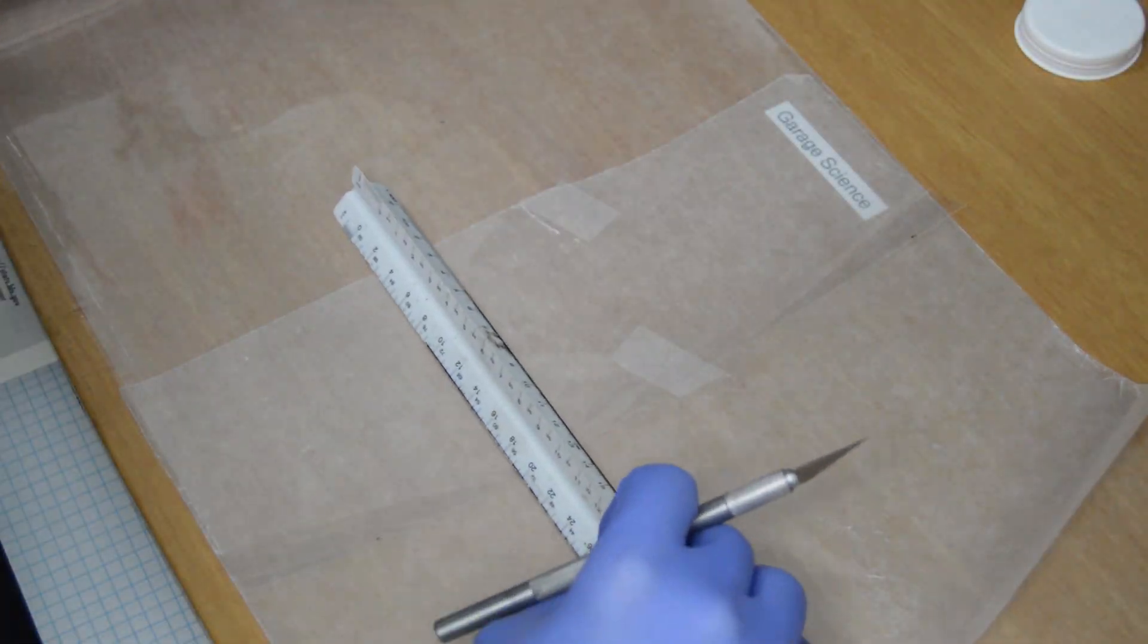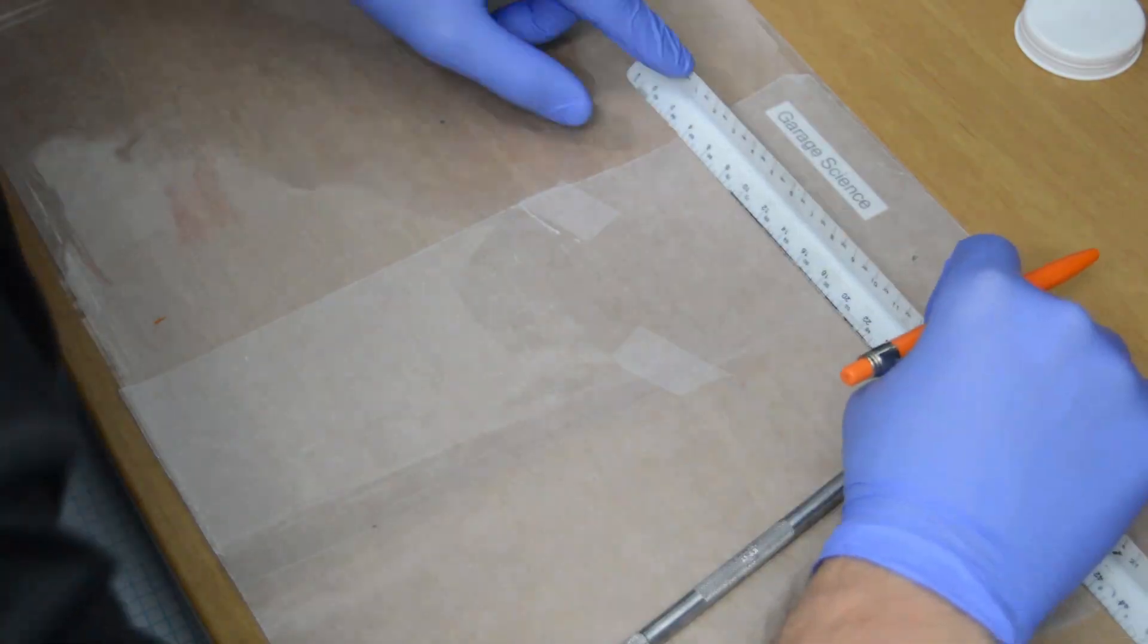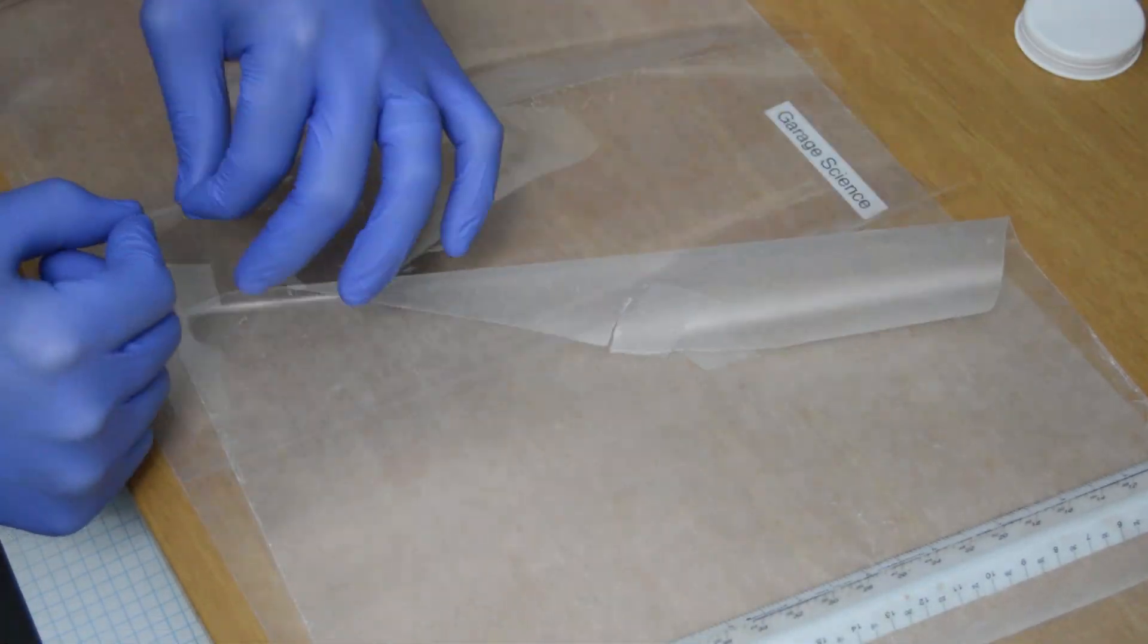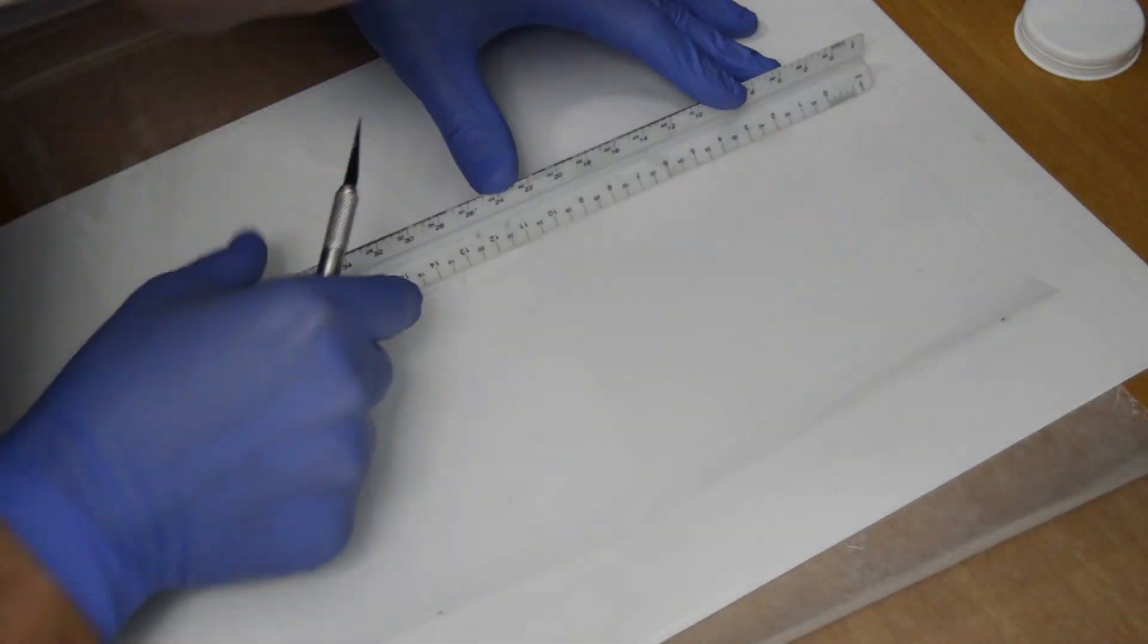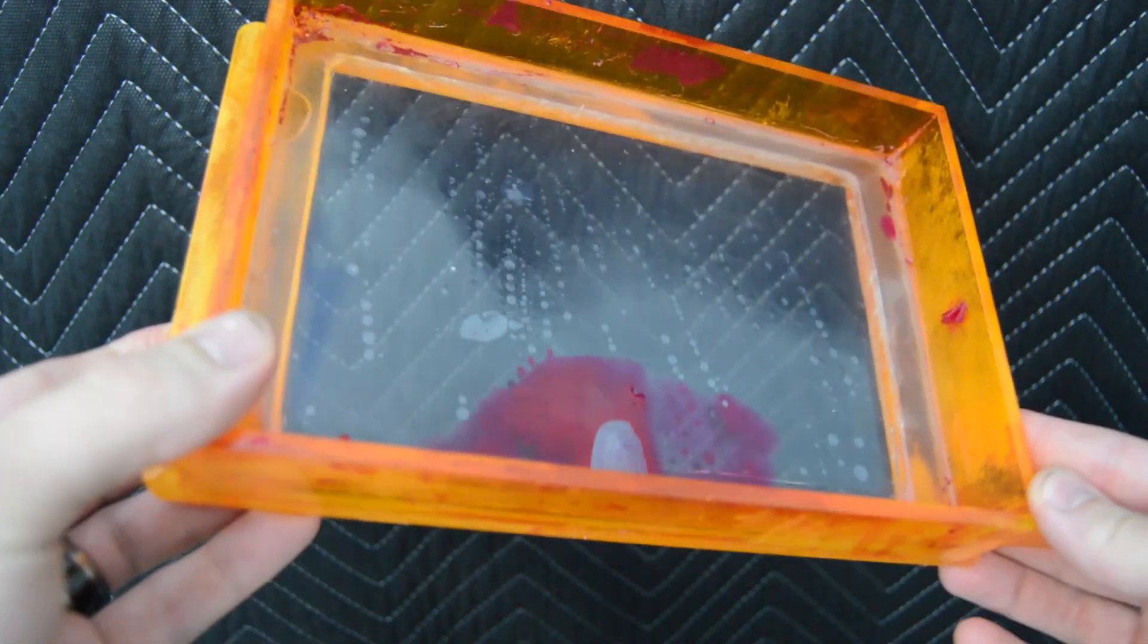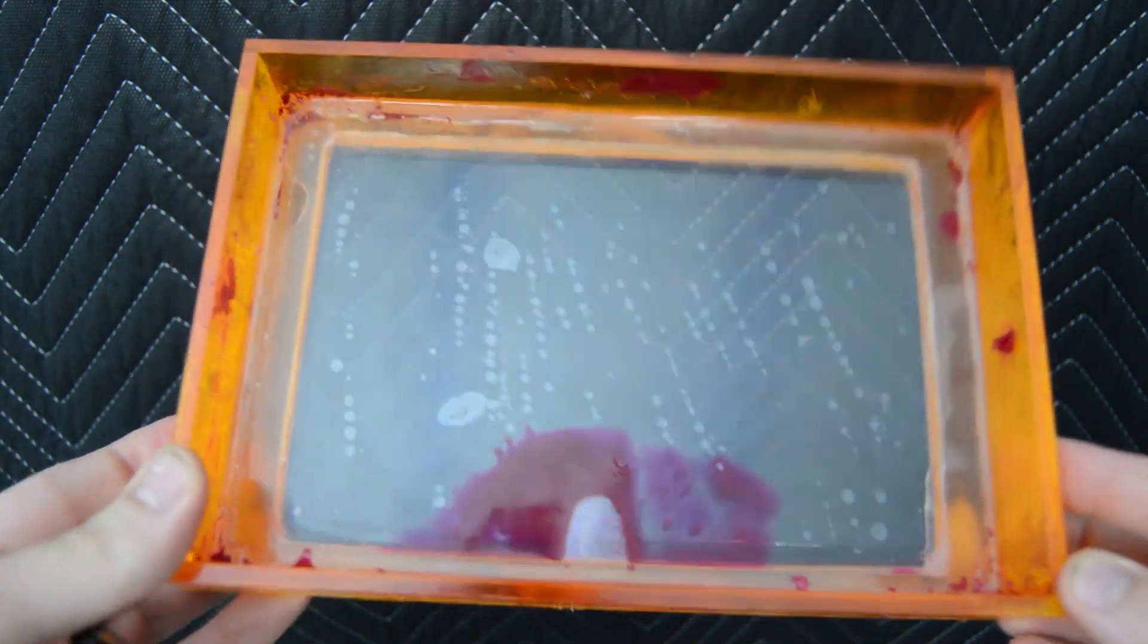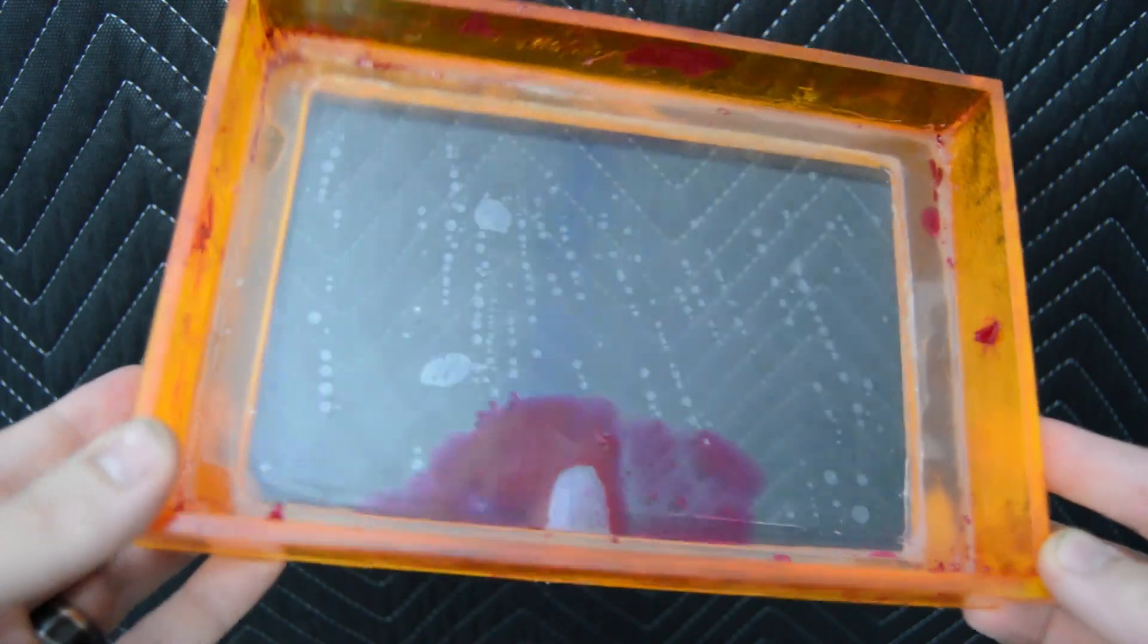In addition to recoating this vat with PDMS, I will also be adding a layer of FEP film also made by DuPont. Do not try and adhere FEP film to the PDMS before the PDMS cures completely. The PDMS curing reaction generates gases that will collect under the FEP film and produce air bubbles under the film. I tried to do this on a previous vat and ended up with a substantial number of bubbles which eventually allowed resin under the film, thus ruining the vat window and requiring a replacement layer of film. The bubbles also distorted the clarity of the vat that affected several of the prints I attempted.